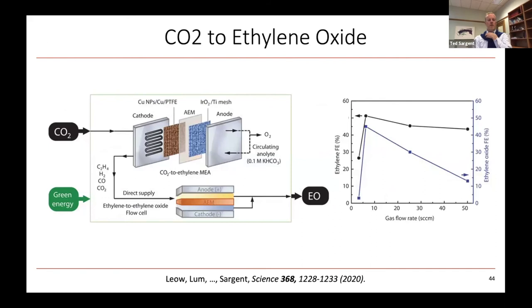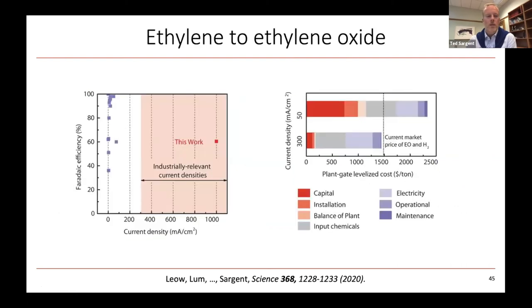So for reasons of time, I'll be a little brief on this, and I'll just say that we were then able to take this system and also couple it to a CO2 to ethylene system, go all the way from CO2 to ethylene oxide. And it is also in that category like ethylene glycol that commands quite a nice market price. And so we were able to take this sector that had done some very nice catalysis that was very selective, but that was limited to the milliamps, and take it out to the amp range using this redox mediator and this kind of expanded heterogeneous homogeneous approach.